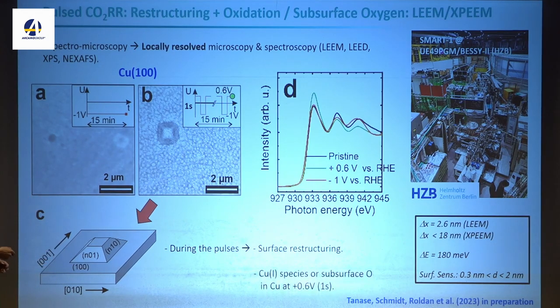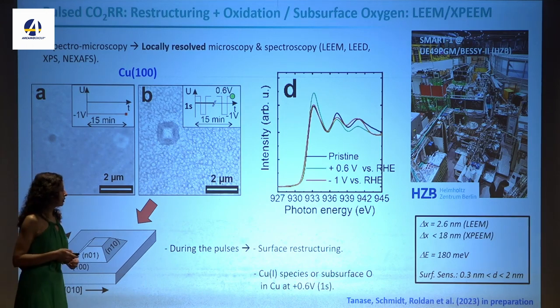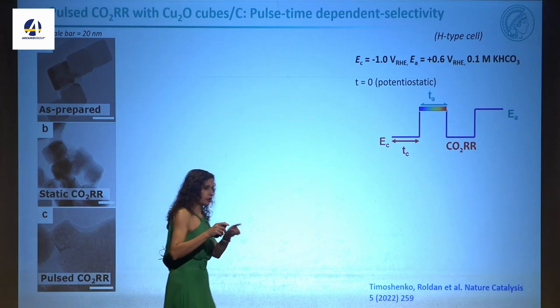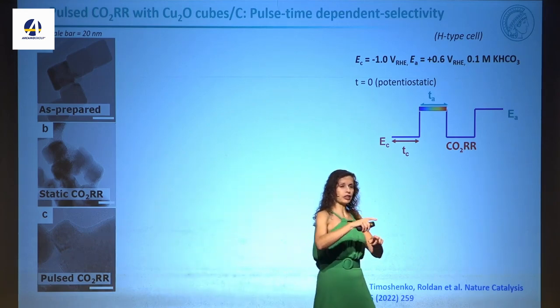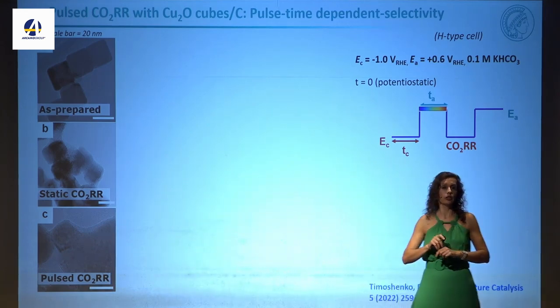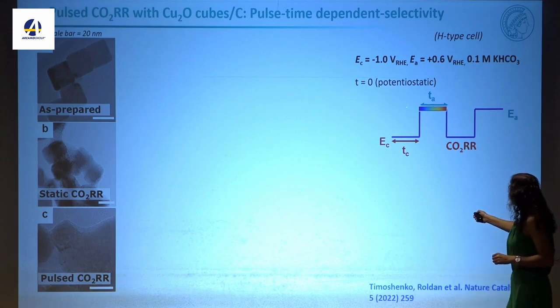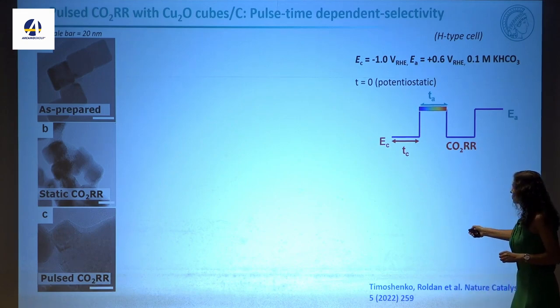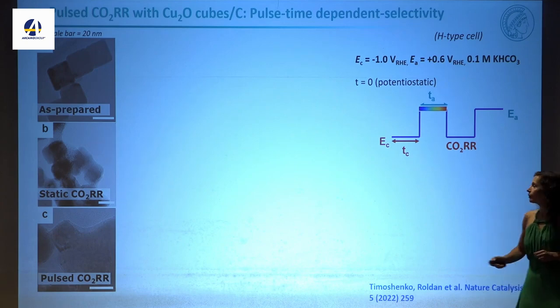In any case, what we could prove is that there are defects created during these pulses, and that there is also a copper-1 species or subsurface oxygen there under reaction conditions. Then we decided to tune this. Now I have the pulses that I can control, whether I'm oxidizing or not, but I can also change the length of the oxidizing pulse versus the pulse where I'm doing CO2 electroreduction. Same catalyst as always, these copper oxide cubes.